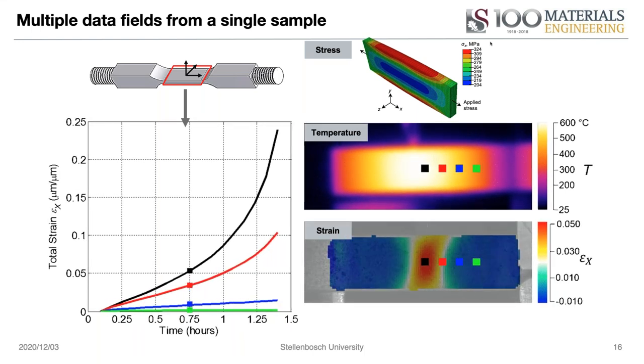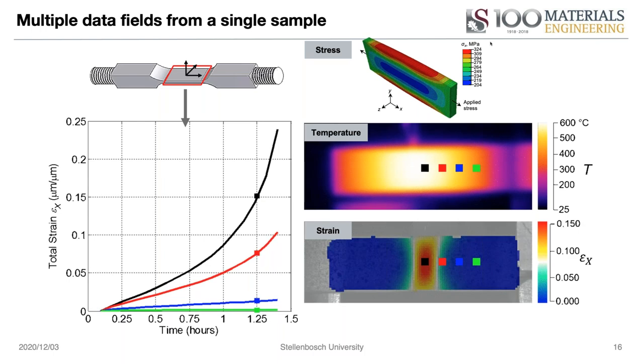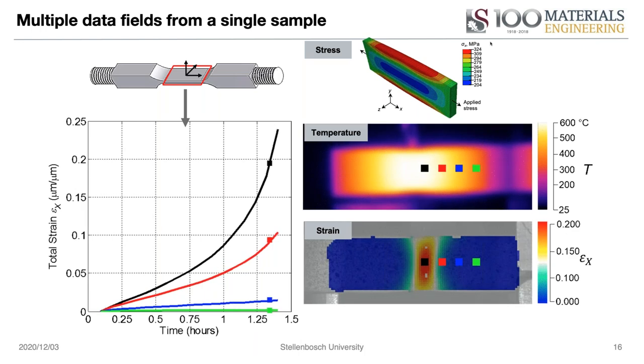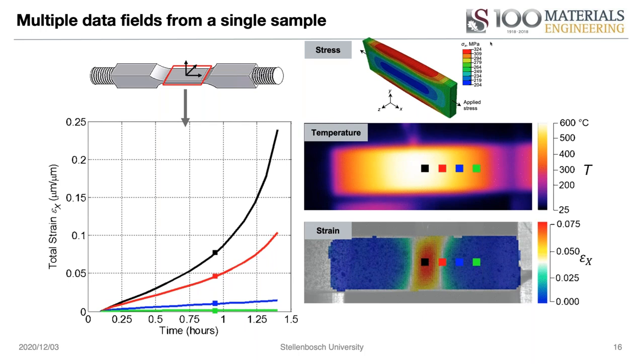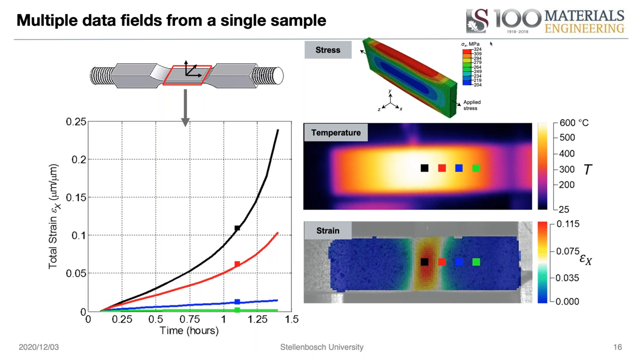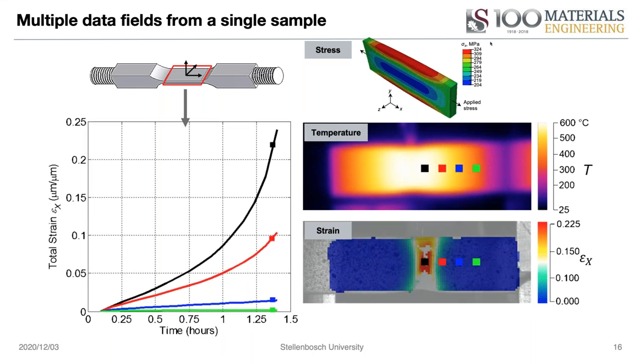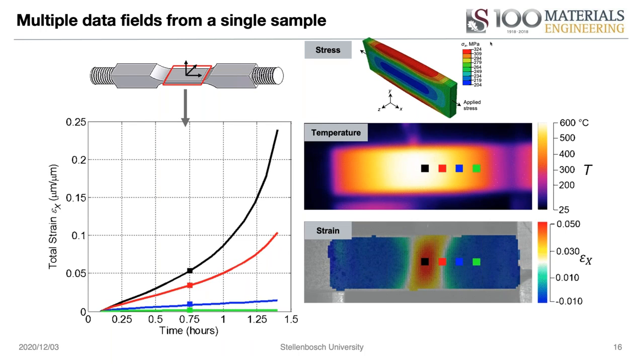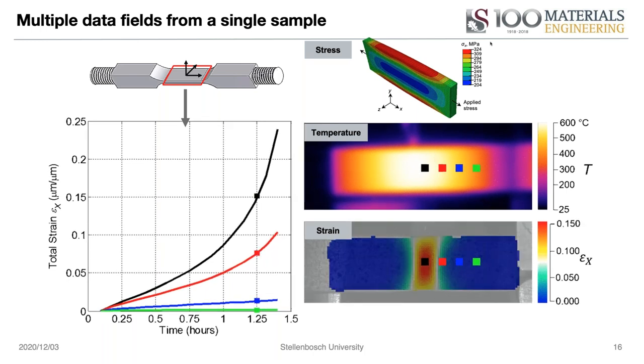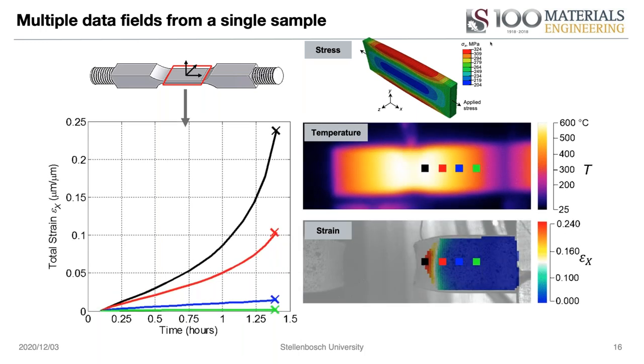It's worth noting the short testing time—less than an hour—which links with the high stress applied as indicated in the FEM model. An important note is that this test is not aimed at replicating creep testing due to the short duration times—the creep mechanisms are fundamentally different. Rather, we want to observe differences in creep deformation rates and link these to the material's damage state, i.e., the material's resistance conditions to creep loading under accelerated conditions.